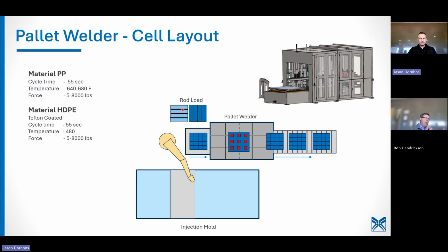We're taking it from that point to get it into the welder in the load position and then through that cycle and out. When you look at materials, if you're looking at a polypro pallet, cycle time is about the same, really about 55 seconds. And the temperature might be 640 to 680 degrees. Force really depends on the weld design, but we can go 5,000 to 8,000 pounds of force on that. So it's going to give you a really strong part.